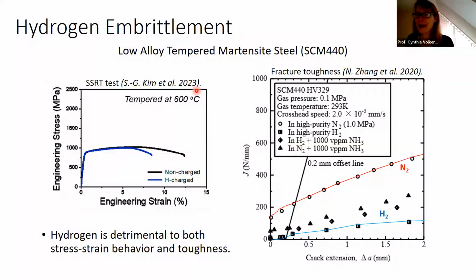And I'll just give a couple of view graphs reminding you all, although I believe you all know it better than I do, about hydrogen embrittlement. The results I'll present today are on a low alloy tempered martensitic steel, so it's in the ferritic state. And the results I'll show are also from this material or ones that are very similar. So the problem with hydrogen embrittlement is exactly that it does what its name says. It's very detrimental to mechanical properties, and you see that here for the case of stress-strain behavior, where when there's hydrogen present, failure sets in earlier. And you see a very marked decrease here in the fracture toughness of the material. And so that's the technological reason why this is so important. It's as simple as that.